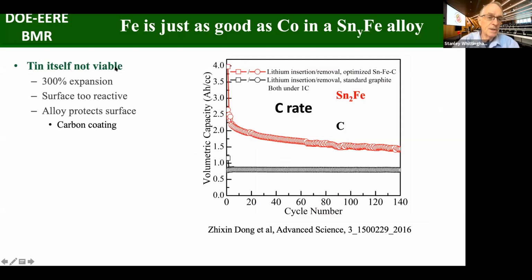Tin itself is not viable. It expands 300%. So we try to protect the tin with carbon coating. So we ground up tin with carbon. But we're using iron balls and an iron vessel. And what we landed up making was this tin iron compound. We made it stoichiometrically, beautiful X-ray pattern. And this is all done basically in a grinding media.